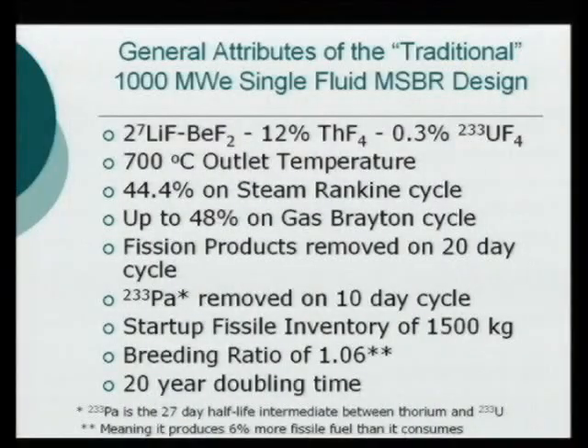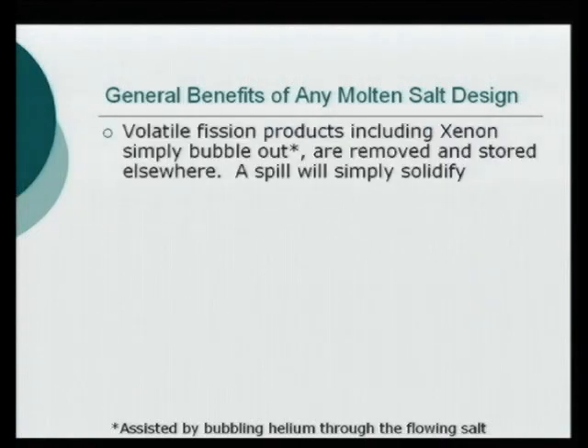That gave a 20-year doubling time, which back when it was in competition with fast breeder reactors was not as good as the fast breeders, but we had to change the fast breeders later for safety reasons, and they're nowhere near as good as 20 years anymore. General benefits of any molten salt design: volatile fission products, gaseous fission products, things that want to come out of the salt will come out as we're operating, and we simply collect them. The most important thing is xenon. It's a gas that really just loves to absorb neutrons.